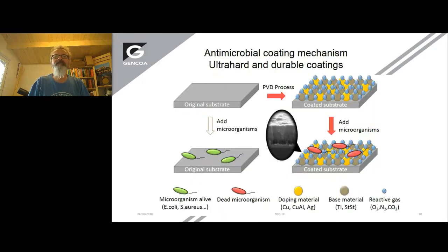And that works by essentially, we test that by putting microorganisms onto surfaces and determining how long they survive for. And we discovered that with this topology we're arranging, we have a very rapid kill rate of bugs on surfaces. And one thing to note here is, traditionally, it's been extremely hard to put an antimicrobial coating onto stainless steel because in terms of durability, stainless steel is great. But it's hard to put something on there that's antimicrobial and extremely durable. So we believe that our coating's micro hardness is harder than stainless steel and it is extremely durable. So we're very pleased with that.